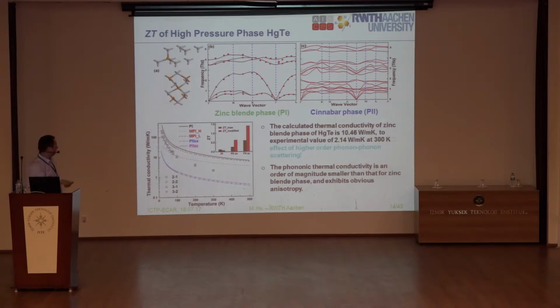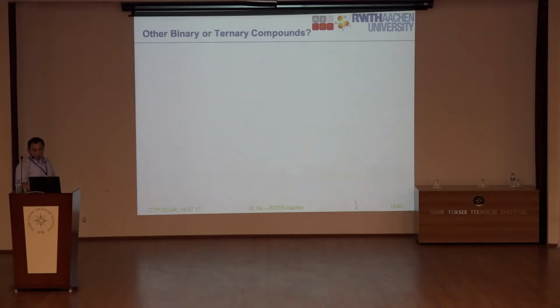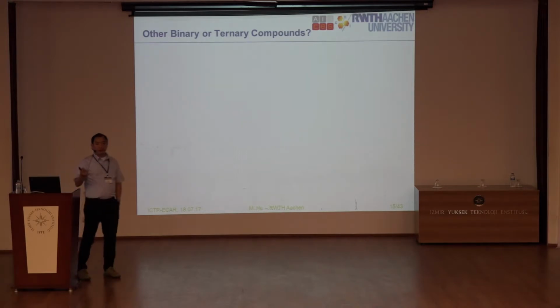And then if you calculate thermal conductivity, you will find that the thermal conductivity goes down significantly, and eventually you can calculate the ZT coefficient, which can be around 1.4 at room temperature. This value is actually so promising compared to lots of other available thermoelectric experiments. So the idea is that, okay, we just find the one special case.